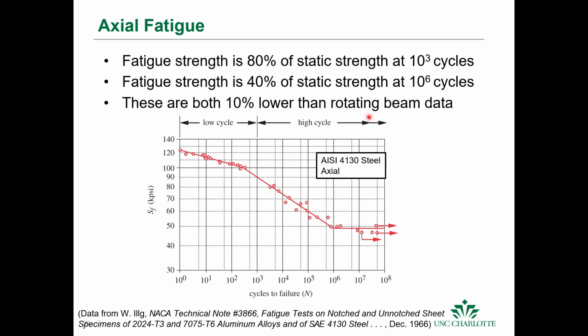The fatigue strength is about 80% of the static strength at 10 to the 3 cycles. The fatigue strength is about 40% of the static strength at 10 to the 6 cycles. At 10 to the 3, we're about 80% of the strength. At 10 to the 6, we're about 40%. And these are both 10% lower than the rotating beam data, in this case for this steel.